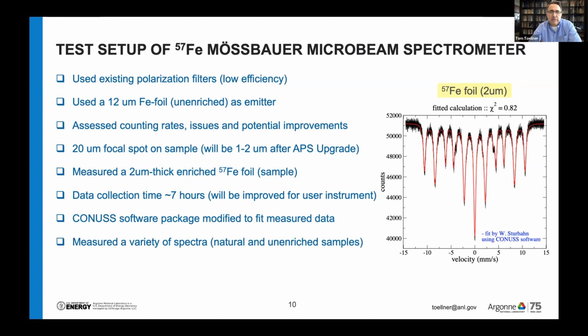This measurement was 7 hours. That sounds egregious because this is like the best sample you can do, but the newer instrument will have a significantly higher data rate. So the collection time will be a factor of 60 smaller than this. So one can expect this spectrum from this sample with this level of data quality to be collected in about 7 minutes with the new instrument after the upgrade.